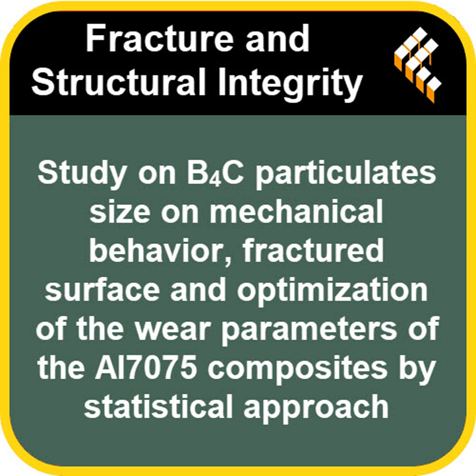But when they did the statistical analysis, the ANOVA, was there one factor that really stood out as controlling wear and friction above all others? Oh, absolutely. The statistics delivered a very clear message. Particulate size was overwhelmingly the most significant factor for wear loss. It accounted for over 61% of the variation they saw, and also for the coefficient of friction, again, over 61% of the influence. Over 60% for both. Yes. It means that for these specific composites, how big those B4C particles are is by far the primary driver of how they perform under wear conditions. Size really is king here. Size is king. Got it.